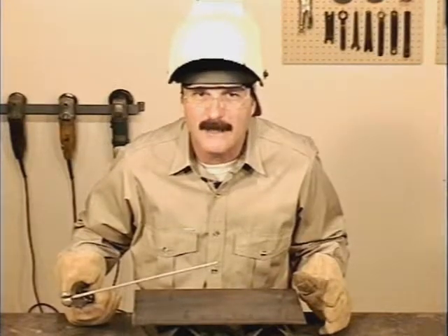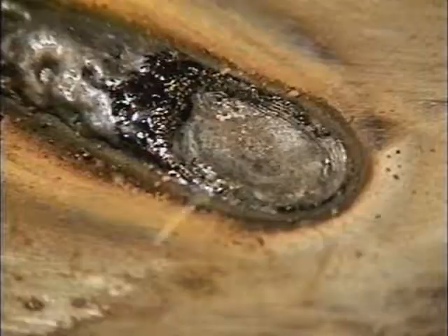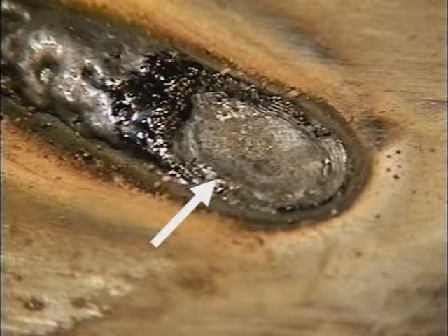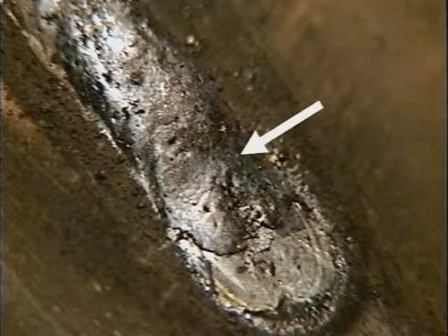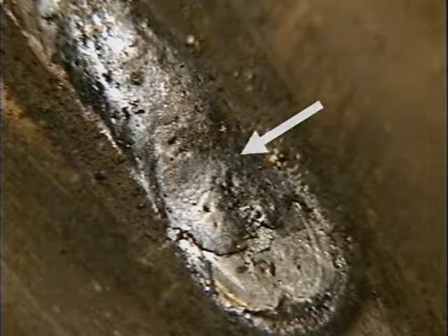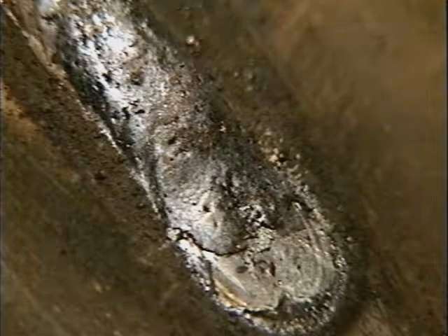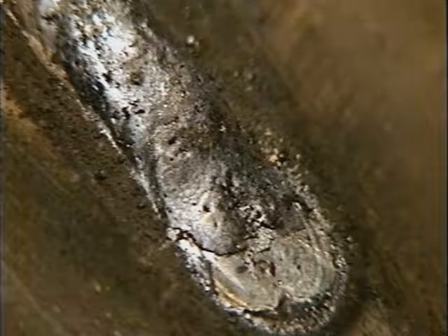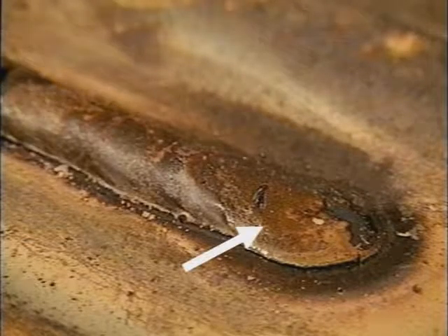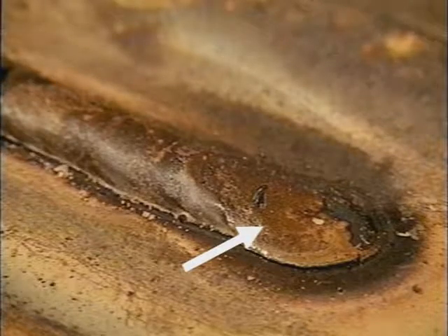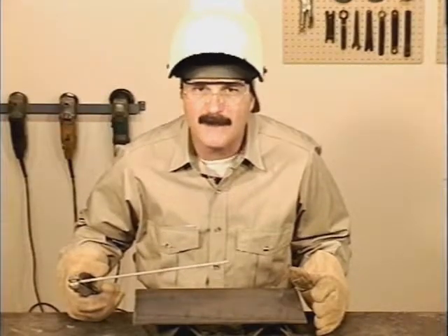With the fast freeze rods, 6010 and 6011, the molten metal in the weld puddle is completely visible. Slag covers the top edge of the molten puddle with 6013, but the filler metal and slag solidify pretty much at the same time. With 7018, the entire weld puddle is covered by molten slag. The filler metal actually solidifies underneath, while the slag stays molten on top. If you keep in mind that what you see is molten slag and understand what the metal is doing underneath, 7018 is fairly simple to use.